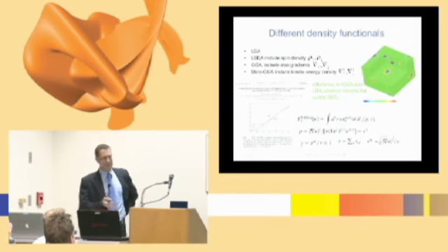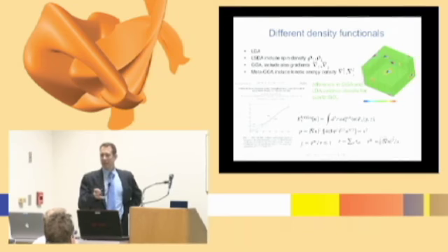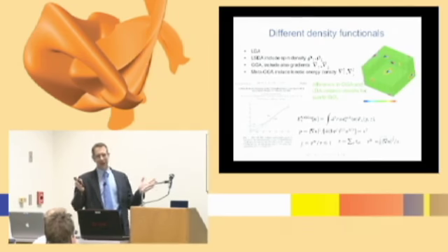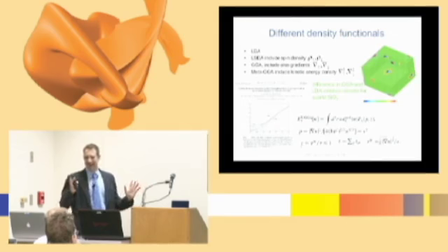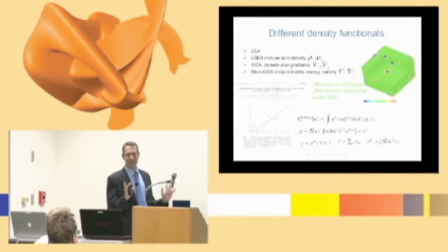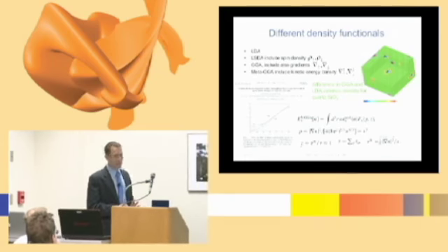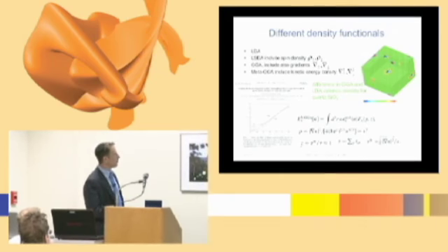Maybe you can convince yourself that in some class of materials you can get a better approximation from that. But if you read a paper in the literature where somebody did the LDA and they got a volume that was 10% larger than experiment, you can say there's either something wrong with the experiment or something wrong with their calculations. Okay, so generally, I don't know of any really good exceptions. The LDA will give you one sign of the error and GGA the other.